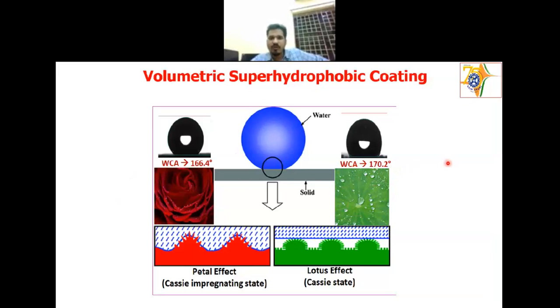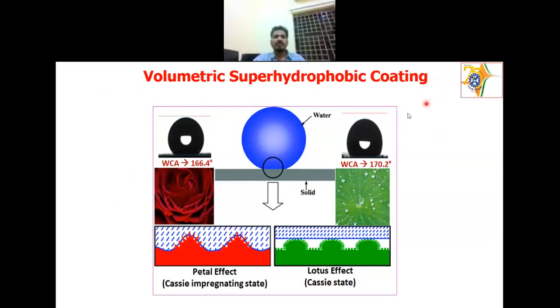And another recent thing we are working on is a volumetric superhydrophobic coating. Accidentally, when we prepared a similar type of formulation, we got two types of coating. One has a petal effect, that is the rose effect, and the other has the lotus effect. Here we can see the rolling of water in the lotus effect sample, but in the rose effect, petal effect sample, there is no rolling because the surface has very high adhesion, but the water droplet is able to sit there. Even if we keep the substrate upside down, the droplet is still adhered to it. It is still in the super hydrophobic regime, a quasi state. It is a quasi state because the water is sitting on air in the lotus case, but here there is no air. The water molecule is able to penetrate through the grooves on the surface.